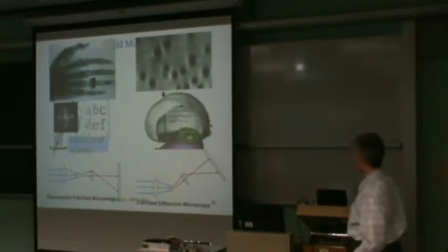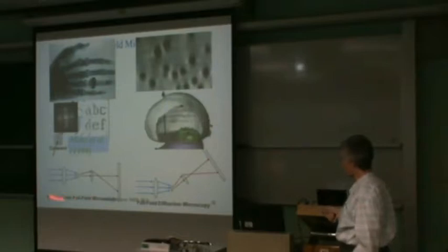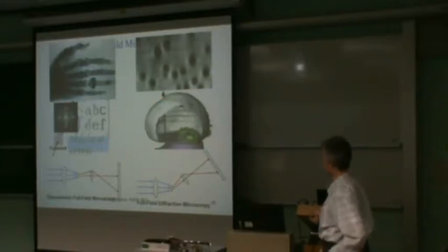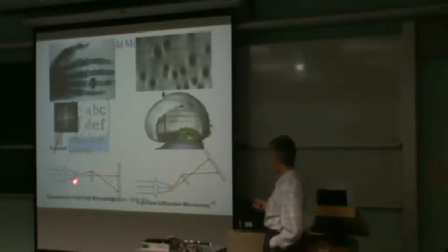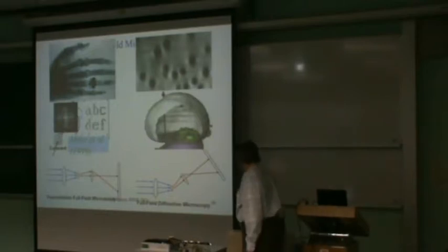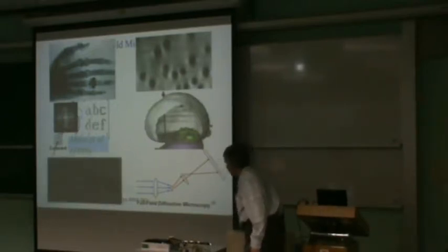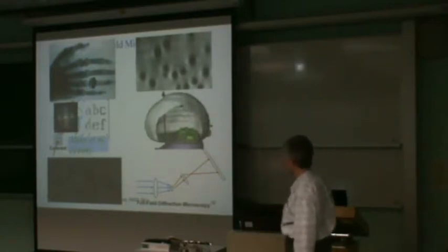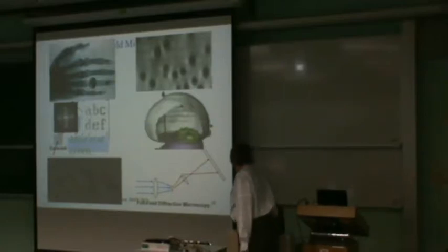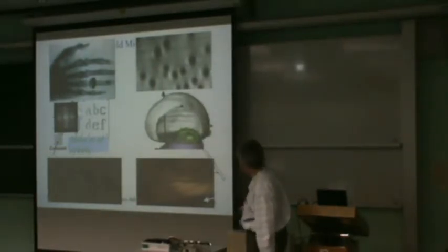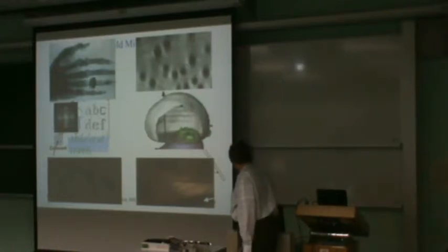I think it was 500 nanometers in diameter. There's also lens-based imaging methods which are very much under development and not really quite ready to talk about or apply in this situation. So we're going to focus on this one. But just to complete the picture, the lens-based imaging is where you put a lens between your sample and the detector, and then you can turn the scattered X-ray beams coming from it into an image. And that, rather dark, but that's an optical bandgap material that's been imaged by that method. And then finally, that can also be done with diffraction as well. And you get images which have got phase contrast. Here it's a little bit dark, but these are steps on the surface that have been imaged by Paul Fenton's group.